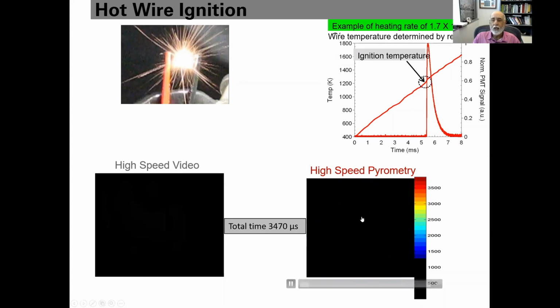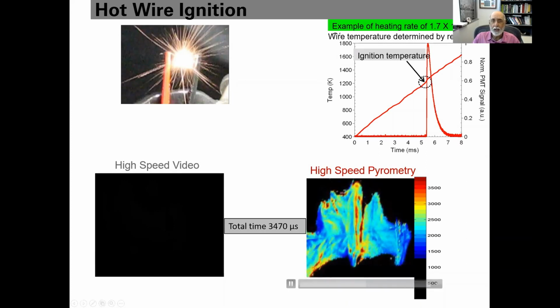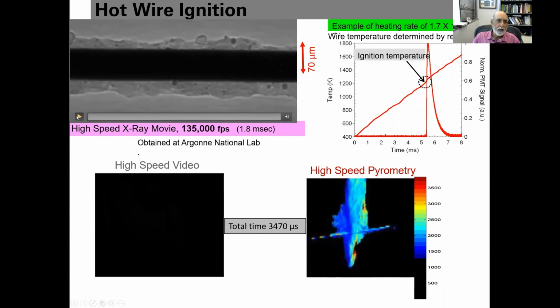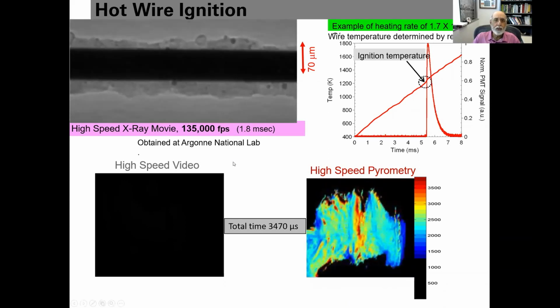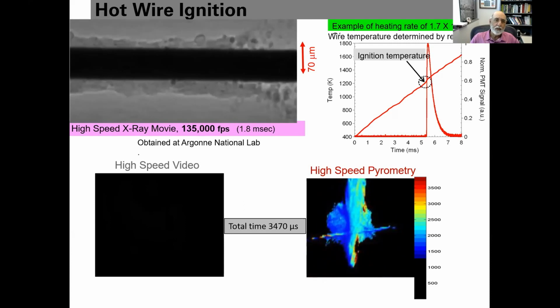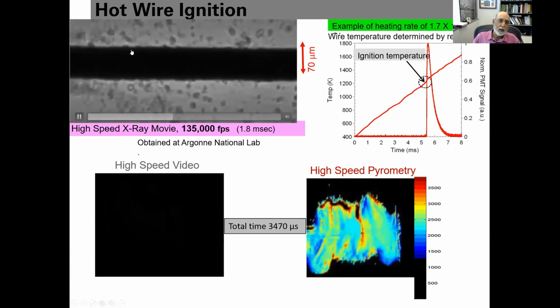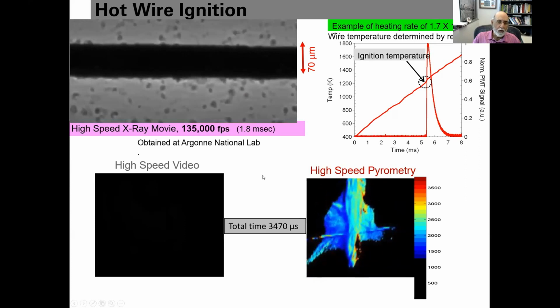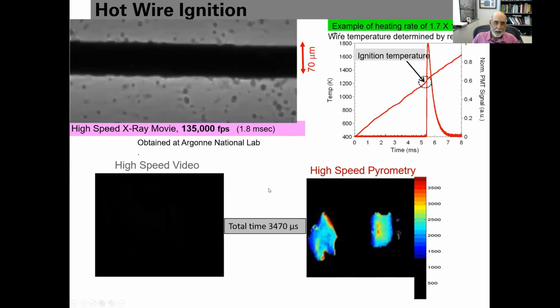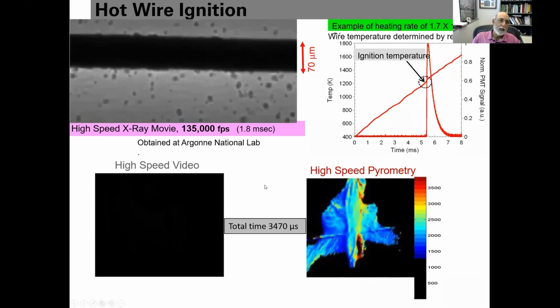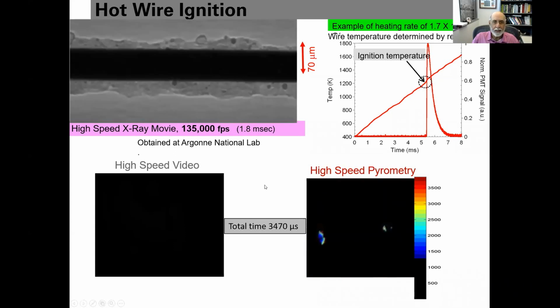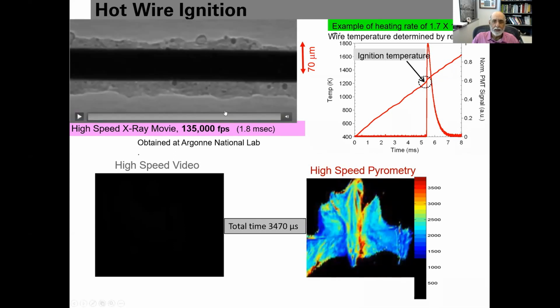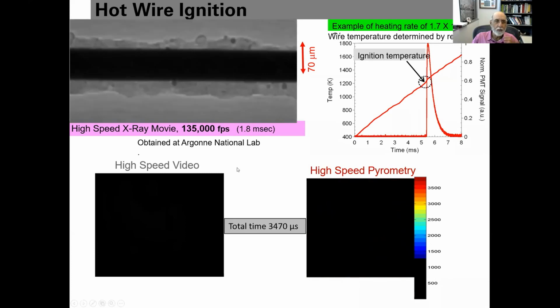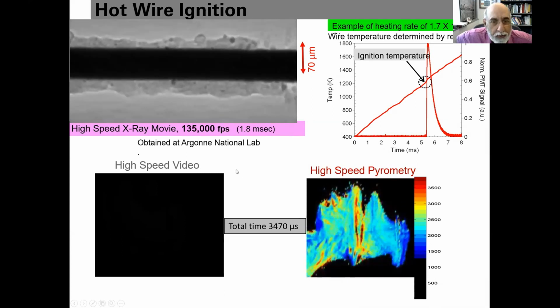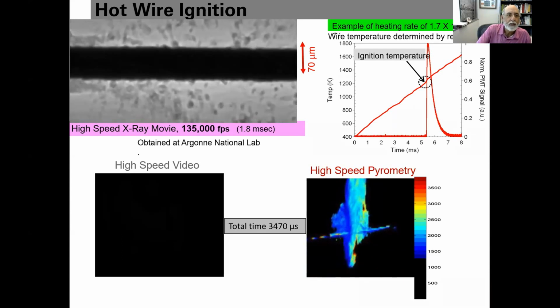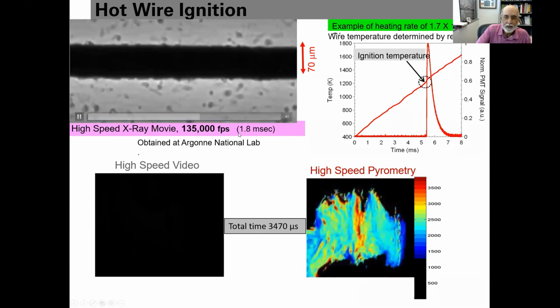You can look spectroscopically at what's going on as well. And if one were to do X-ray imaging, this is what happens on the wire as I heat the wire. This is a total time of 1.8 milliseconds. You can see the material coming off the wire and reacting and combusting. Just show that one more time. This is an X-ray image, but you can see what's going on in the system.